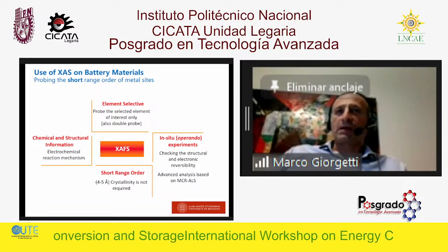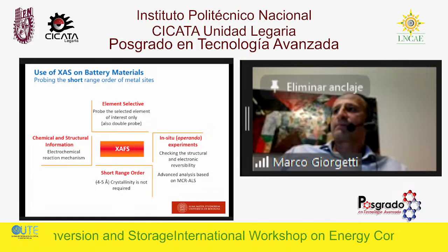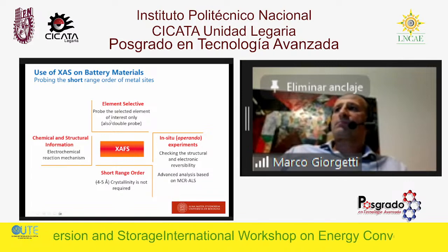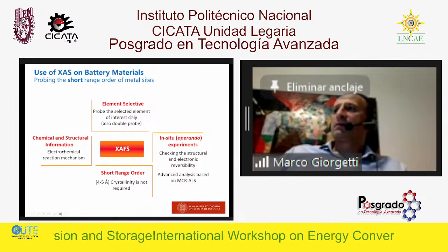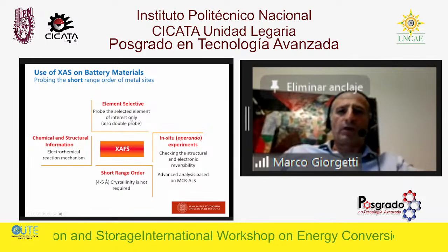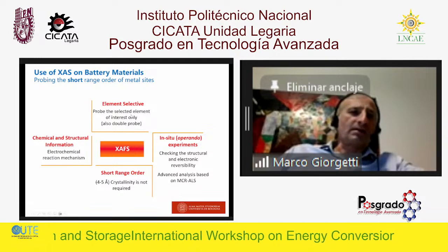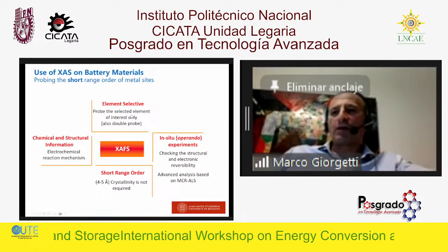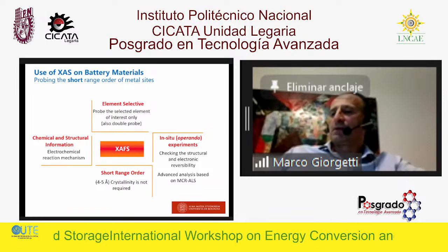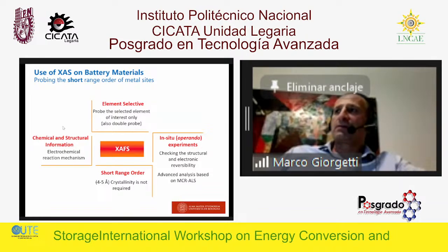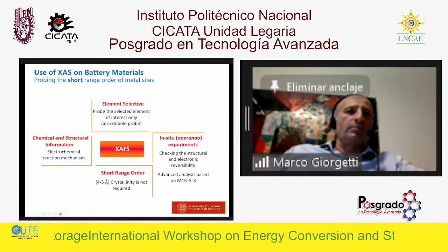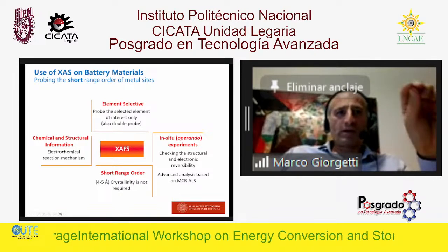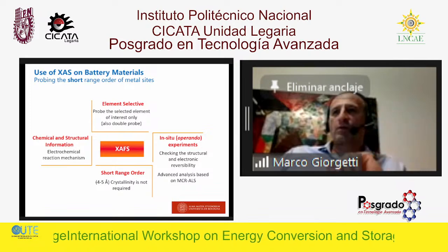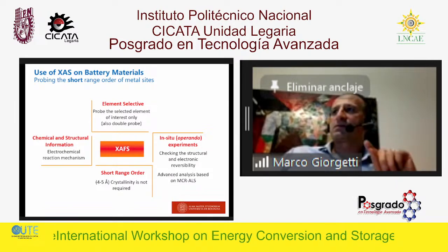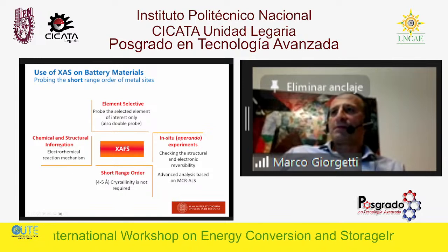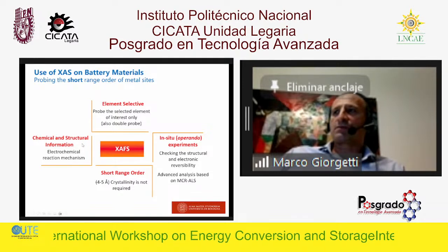This is interesting in battery materials because, first, this is called element selectivity. If you have more than one metal, as in the case of metal hexacyanoferrates, as you know so well, iron and then maybe some other one, copper, cobalt, and whatever, you have a double probe. You can tune your X-ray beam on one core, then put your X-ray beam on another core, and see what is around. So this is element selectivity. It provides chemical and structural information.